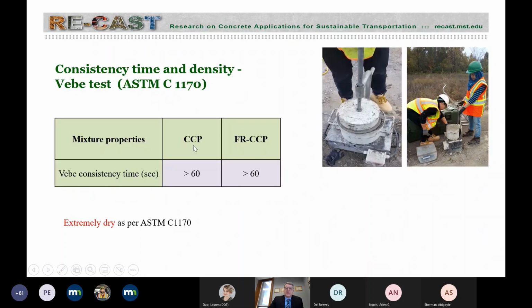In both cases, with the CCP mixture and the fiber CCP mixture, we had to stop the test after 60 seconds. So we can consider this the same thing that we saw in the Vebe test, that both of these CCP mixtures, in my opinion, were too dry. The consistency was not high enough. And we saw earlier if the consistency is moderate, like 45 seconds, you get higher density and you get higher compressive strengths out of your strip.